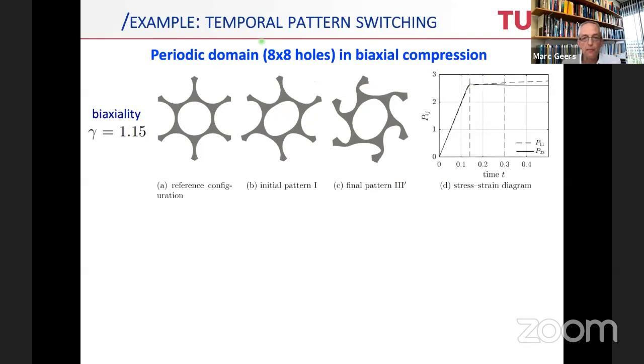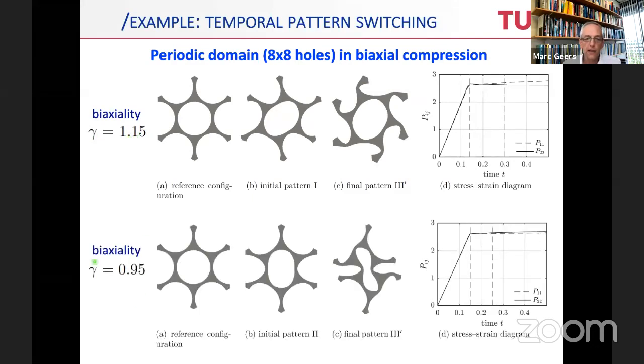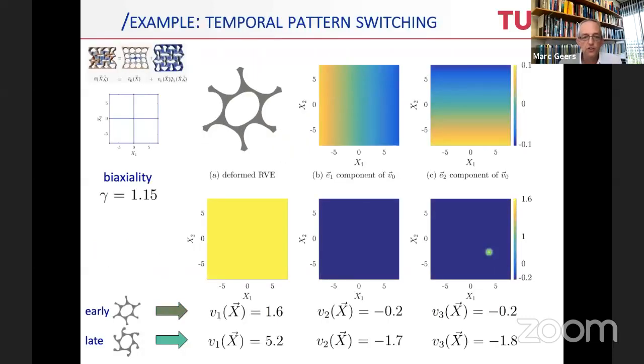First of all, we're going to look at the temporal pattern switching. So two different states of biaxiality: a gamma just above one, and a biaxiality just below one. We start off from the same reference configuration on the left. It develops an initial pattern one here, and here a different pattern two. And if you go further, this one goes to pattern 3, and also another pattern 3' for the other biaxiality case. And here on the right, you can also see that the mechanical performance is of course drastically changing upon pattern formation.